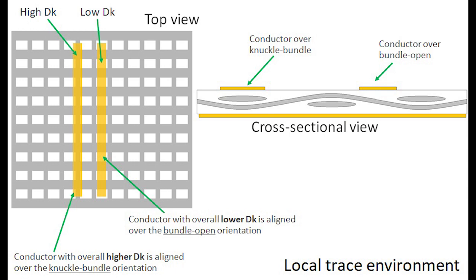Then to the right of that is a conductor that's aligned over an area where there are open areas of the glass, then a bundle area, and then open, bundle. Because of that, the trace on the right, labeled low Dk, will have a lower dielectric constant than the trace on the left labeled high Dk. These two circuits would be on the exact same material and the same circuit, yet they can have very different dielectric constant performance, especially at millimeter wave frequencies where the wavelengths are very small and more sensitive to these Dk differences.